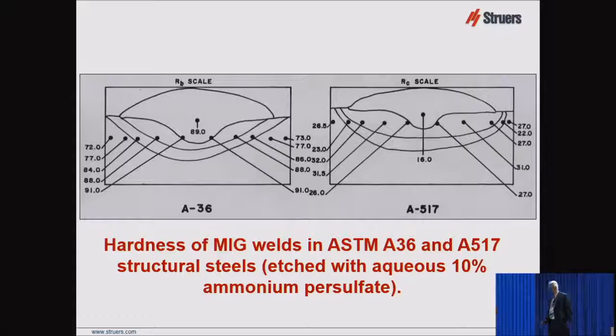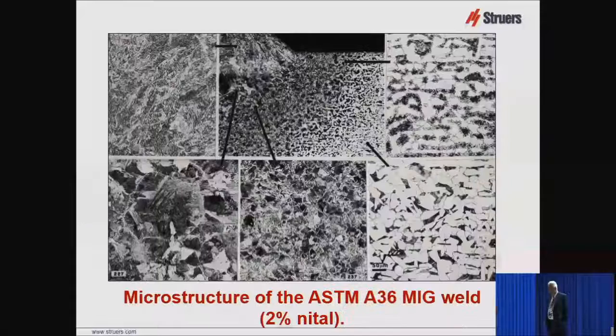And over here, of course, this is higher strength material. We're in the Rockwell C scale. The Rockwell B scale begins below 20 Rockwell C. And over here we're at 26.5. Over here we're 27 Rockwell C in the base metal. And of course it's going up to 26 or 27 right near the fusion line. And the weld metal itself is below the Rockwell C scale right there at 16. So that's technically not a valid number, but it gives you an easy comparison to the other data.